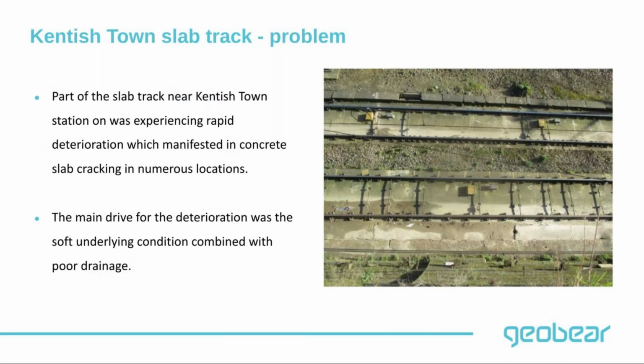I should also note that this slab was built probably around the 60s or 70s, so it's quite an old slab. And as a result of the dynamic action of the track and of the train, combined with the soft underlying conditions and poor drainage, the slab started to crack.